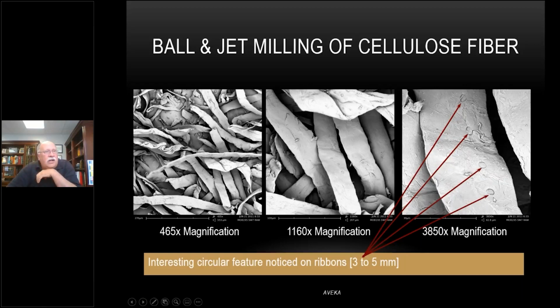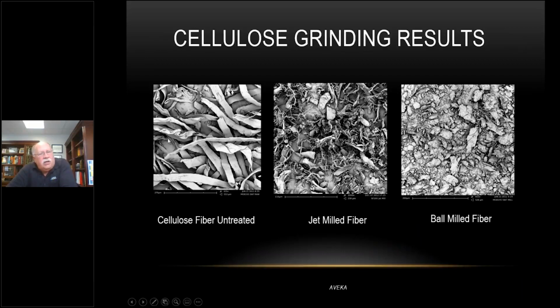These holes that I'm showing here are actually the ports that water enters and leaves fibers, and it was interesting that we were actually able to see this. Now, what we did is we started out first and we ball milled the material. I'm going to show you the pictures on this next slide. So once again, I have the untreated fiber here. You can see it here. And after ball milling, basically we see size reduction.